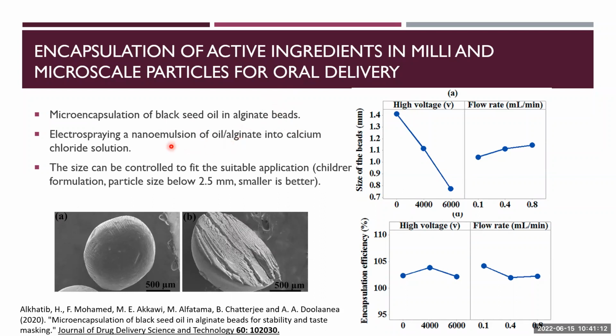Here, we electrospray a nano emulsion of the oil in alginate into calcium chloride solution. Basically, we put in the syringe the nano emulsion that we prepared using this black seed oil in sodium alginate solution. Then we electrospray it into calcium chloride solution. Calcium will cross-link the droplets of alginate, converting them instantly into particles. The size can be controlled to fit the suitable application. For example, for children's formulation, we need a particle size below 2.5 millimeters, and we also prefer it to be smaller.